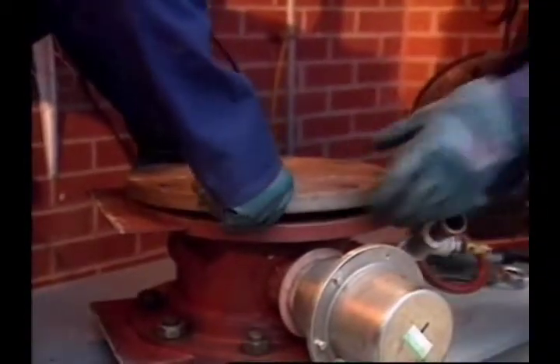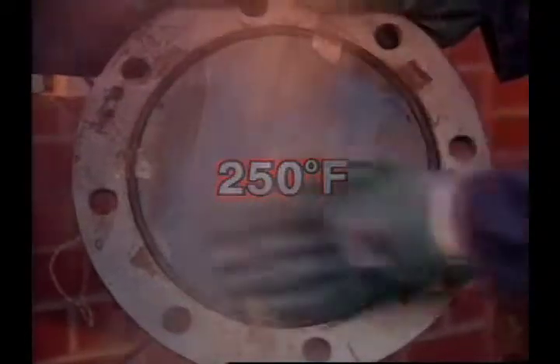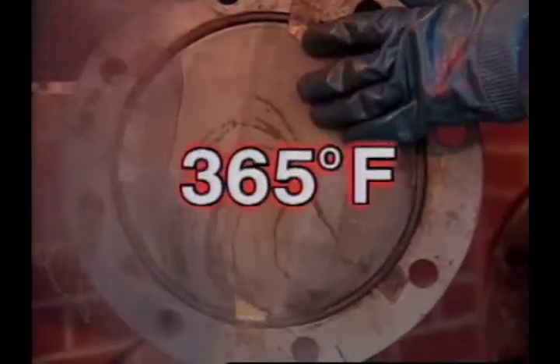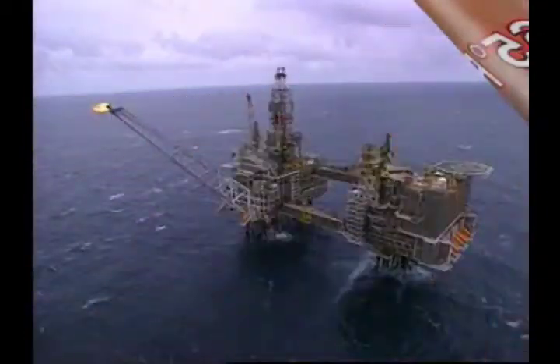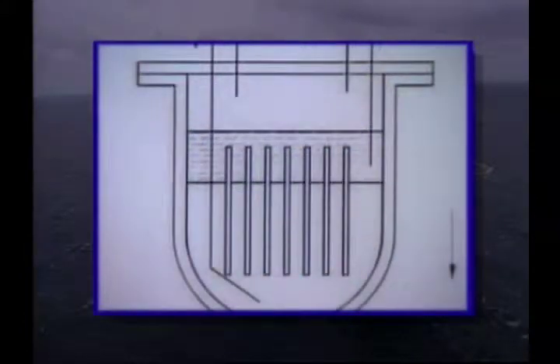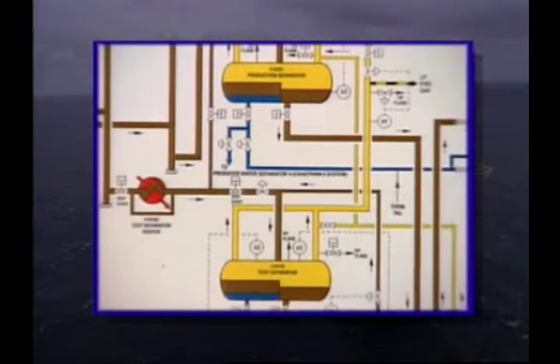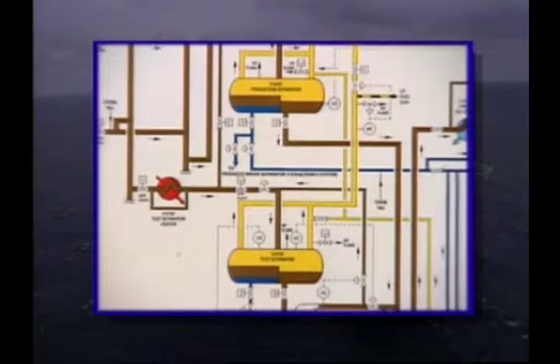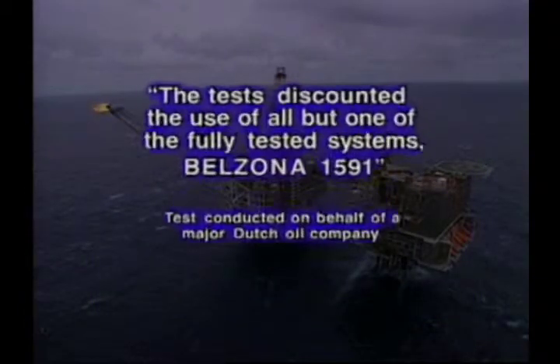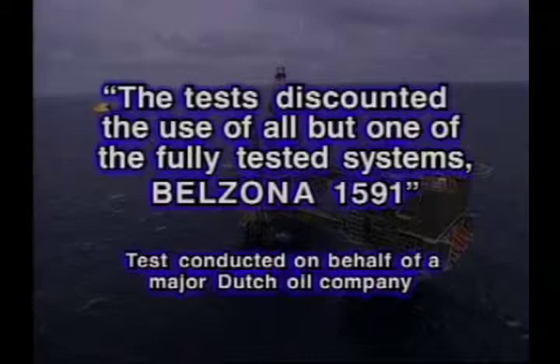This testing showed that Belzona 1591 was the only product to withstand temperatures in excess of 250 degrees Fahrenheit, and when externally insulated, was unaffected at the upper test temperature of 365 degrees Fahrenheit. The technical superiority of Belzona 1591 has been further confirmed by independent testing by and on behalf of major oil and gas companies. For example, in work carried out by a leading British test house on behalf of a major Dutch oil company, Belzona 1591 was compared against coatings recommended by various manufacturers as being suitable for the internal coatings of oil-gas separation equipment operating at 270 degrees Fahrenheit and 450 psi. Even at these relatively low temperatures and pressures, Belzona 1591 was the only in-situ applied and cured coating to withstand